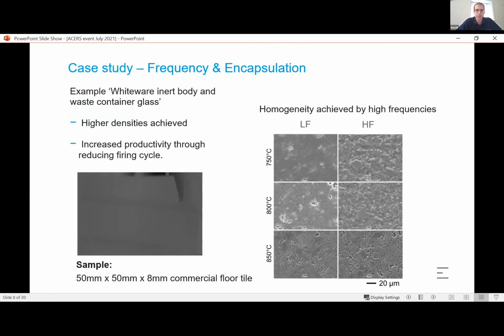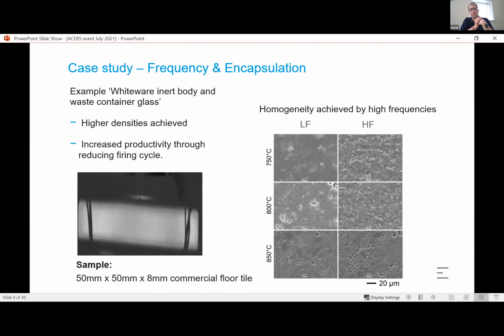If we think of more traditional ceramics, maybe that is an inert body surrounded by liquid phase or vitreous phases. In our case, this formulation is a waste container glass, so recycled glass. We have to have a very different approach because we're using liquid phases that love to localize. So we actually pulse the sample with energy here. And this is a 5 by 5 centimeter tile that's 8 millimeters thick, sandwiched between two electrodes again.